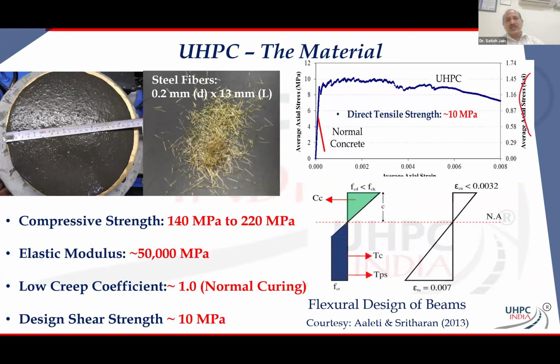And when you talk about it, I'll straight away take you to the pic at the top right, which shows axial stress versus strain curve, and you are simply able to see the difference over there, right? When you have concrete, it can gain some tensile strength, and then you have a brittle failure. Whereas in UHPC, it gains the strength, and then you have a post-peak strain hardening behavior up to some point before you get the strain softening. In effect, you get an almost rectangular curve in the stress strain behavior.